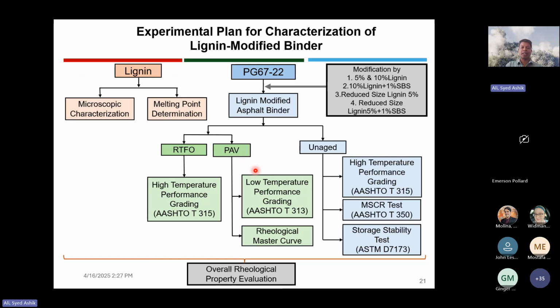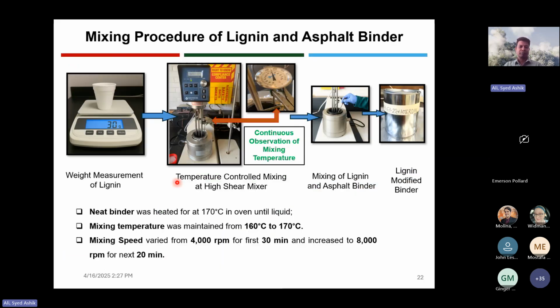And on the PAV sample, which represents the long-term aging, we used the BBR test, bending beam rheometer test, to find out the low temperature properties. And also we conducted the rheological master curve to find out the difference between the neat binder and the lignin modified binder. And then overall, from the whole testing, we try to understand how the rheological property has been impacted by the addition of lignin.